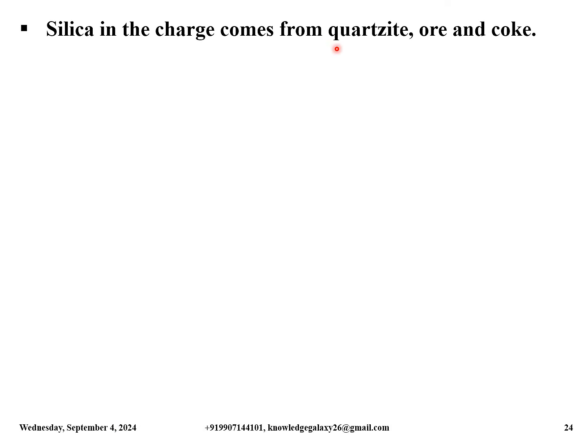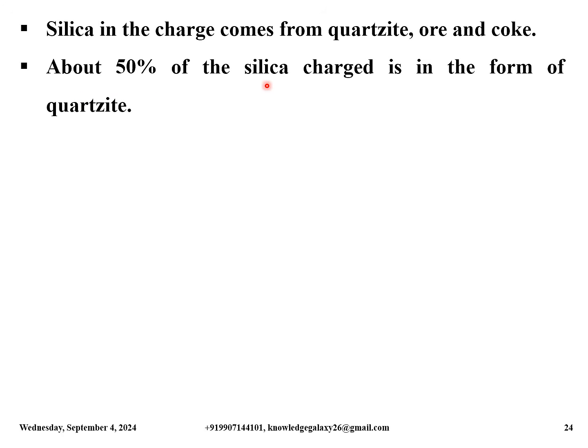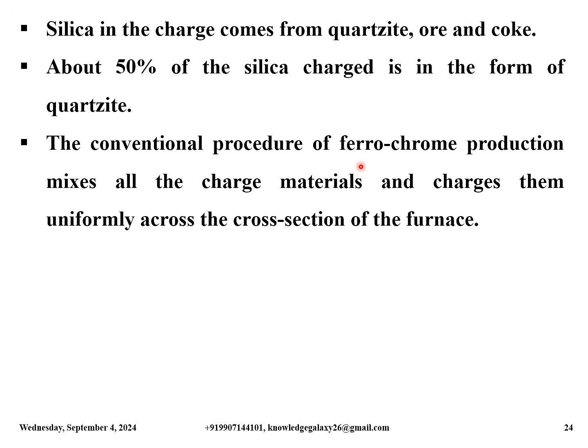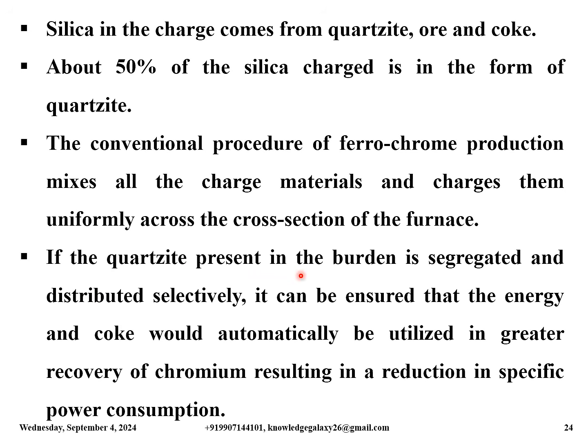Silica in the charge comes from quartzite, ore and coke. About 50% of the silica in the charge is in the form of quartzite. The conventional procedure of ferrochrome production mixes all the charged materials and charges them uniformly across the cross section of the furnace. If the quartzite present in the burden is segregated and distributed selectively, it can be ensured that the energy and coke would automatically be utilized in greater recovery of chromium, resulting in a reduction in specific power consumption.